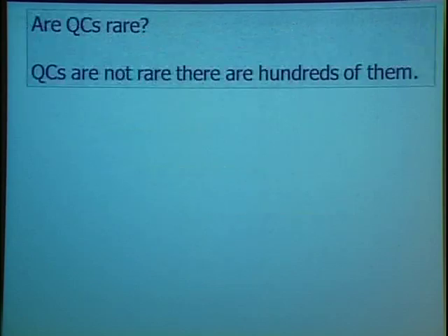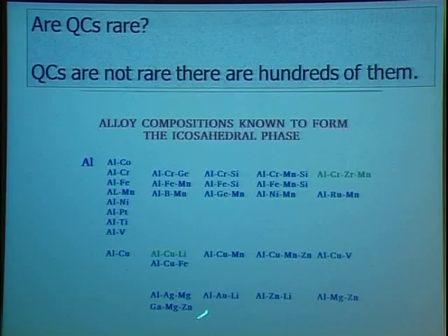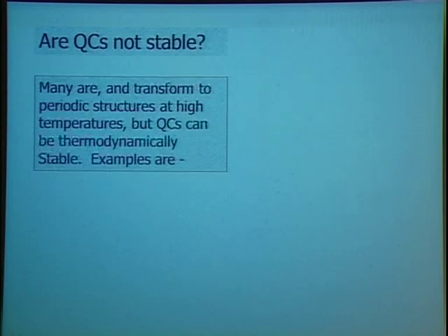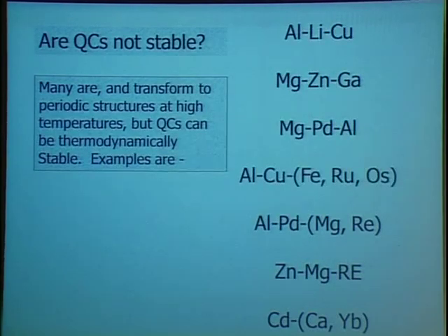Well, number one, they are not rare at all. There are hundreds of quasi-periodic materials, hundreds and hundreds of them. Here is a partial list of quasi-periodic compositions based on aluminum alone, and there are many that are based on other elements. Not rare. This is not the reason why they were not discovered. Maybe they're not stable? Well, many indeed are not stable, but what does it mean, not stable? It means that if you heat them up to 350 or 400 degrees C, they will transform to a periodic phase. But at room temperature, they're stable, no problem. And there are also quite a few compositions which melt congruently, which means that they are stable until the melting point. All right? So this is not the reason.